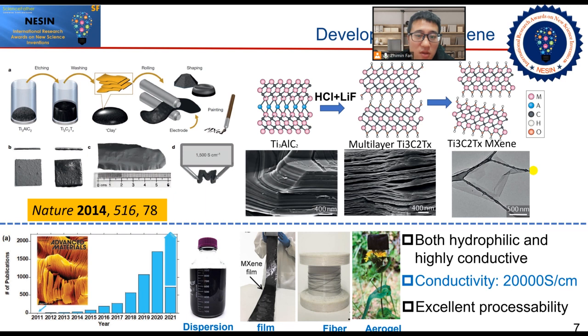Subsequently, in 2014, they developed a method to generate hydrofluoric acid in situ using lithium fluoride and hydrochloric acid, which can easily prepare monolayer MXene with high yield and few defects. So far, MXene has entered a field of rapid development.